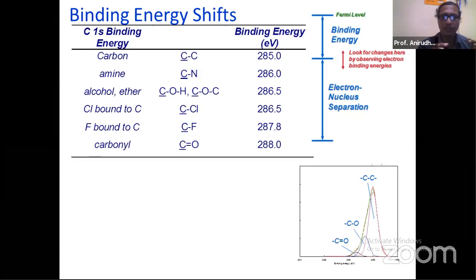So the points to be noted are as follows. If you are looking at carbon when it is in unbonded form, that means in elemental form, not in compound form, its binding energy has one value. Now, when there is bonding for carbon, there is a shift in its binding energy from its parent value of 285 to values like 286.5, 287.8, etc. Those shifts in binding energies are indicative of the chemical coordination between carbon and different other elements, which as an investigator you would suspect to be on the surface.